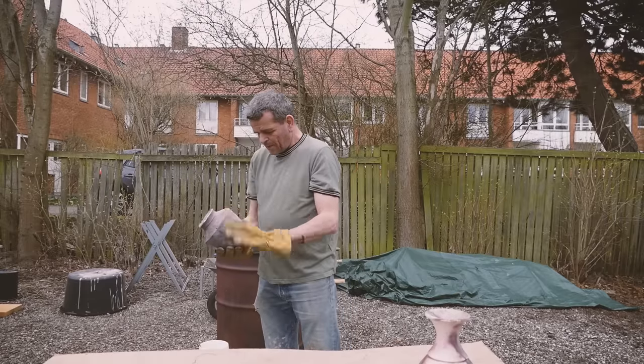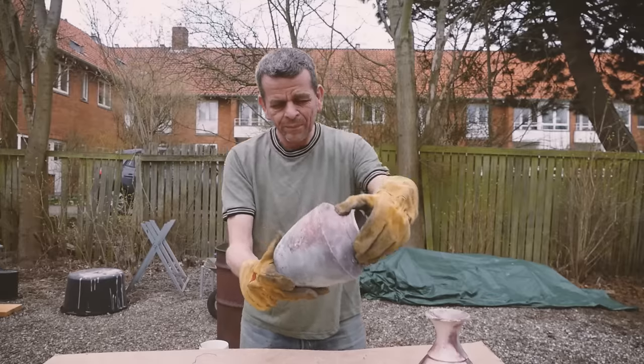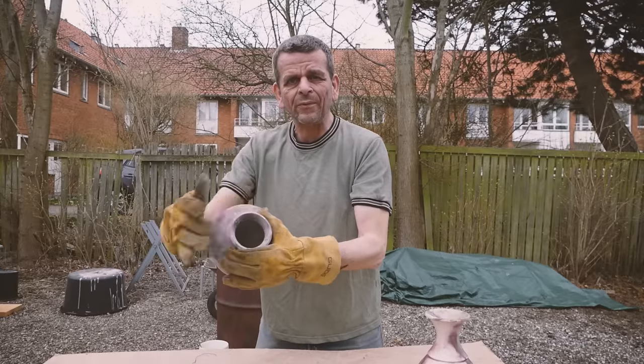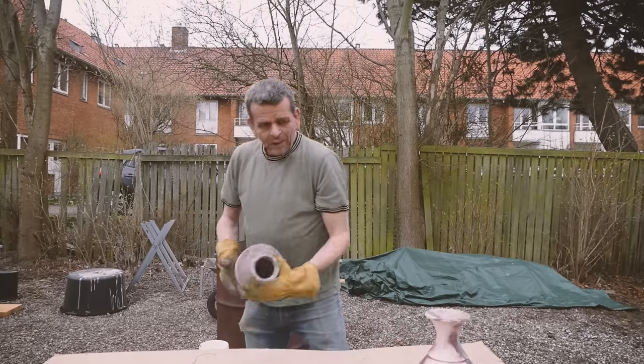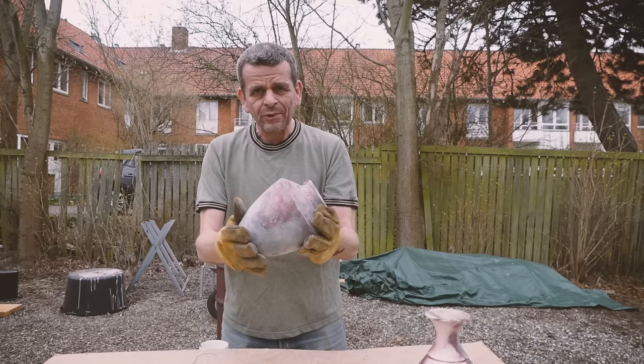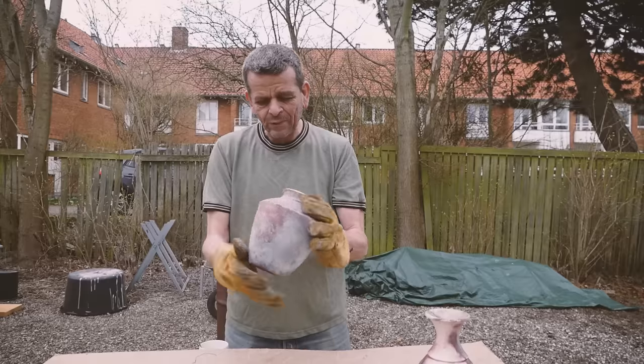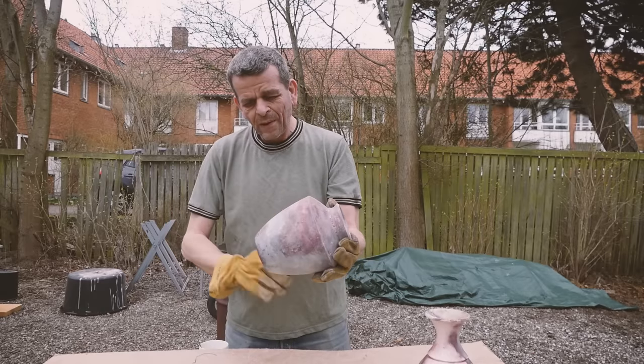This is the one we didn't wrap in tin foil but only in newspaper. This is different — some interesting grey areas here, but still some nice reds. There can be a lot of ashes inside, and if you have to put sealant in there you want to make sure it's clean. Some people wash them in water, but I don't like to do that because if you wash them, remember it's not sealed — so that's going to soak into the pot. You'd have to let it dry at least some days, maybe a week or two, before you can apply any polishing; otherwise you're going to trap the water in there. I like to just lightly brush them, maybe with a little brush, to get all the dust away.